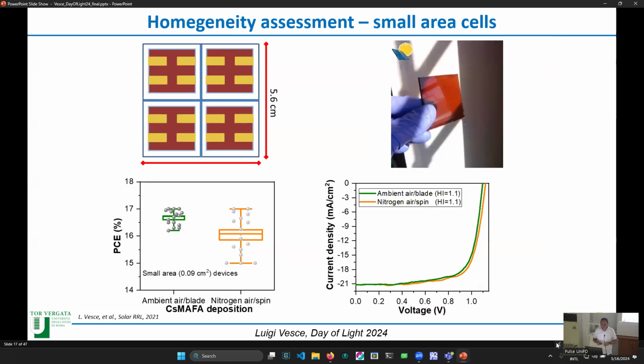And also we realized an electrical homogeneity assessment. So we realized different cells in different portions of the substrate. Here, this is not a module, but on the side of a module, we realized different cells in different parts of the substrate. In this way, we can compare if the performance has not so big an error.